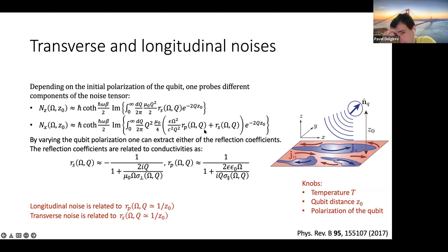One additional point that I want to make here is that you may see that there is integral that is over all modes that contribute to the noise. But actually what happens is that among the waves that contribute, the dominant contribution comes from so-called evanescent waves. And in turn, it means that there is exponential cutoff here, which sets momentum roughly to be 1 over z0. I'll come back to this point in a minute.